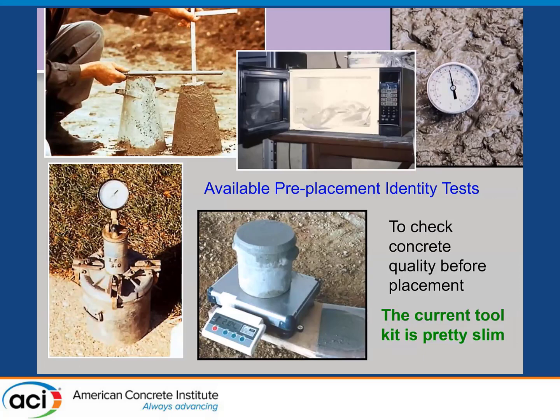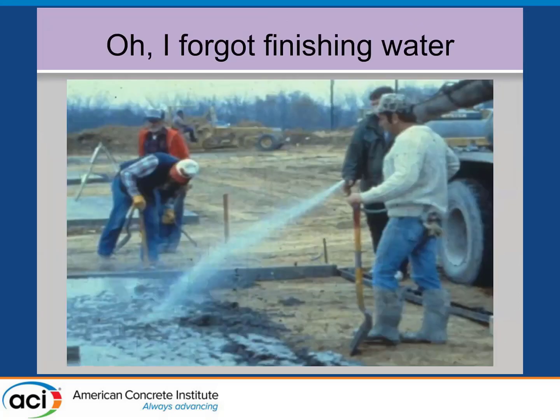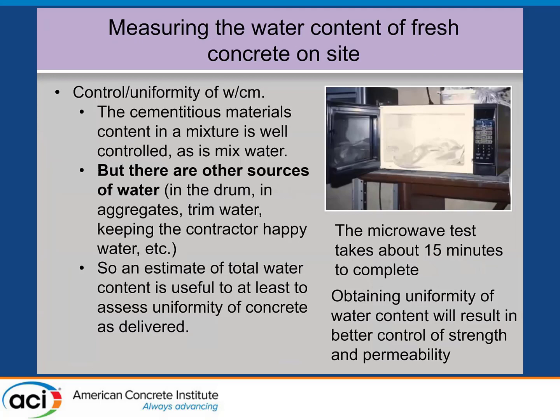Okay. One of the biggest problems we have is measuring water. We have water cement ratio specs, but we can't measure it. The only test method, and AASHTO has a standard for this, I know CSA has one too, is the microwave test for water content. Because cement materials and all the solid materials are generally well controlled at the batch plant. And mix water is well controlled at the batch plant. But then after that, we don't know what else water is in there.